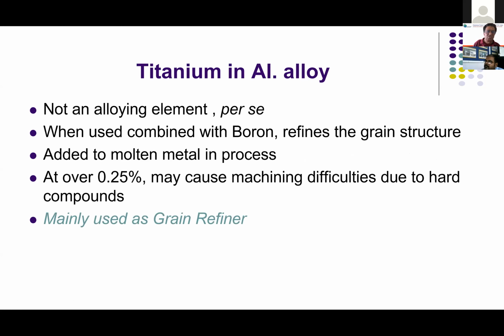Titanium, per se, is not an alloying element, but it improves along with the combination of boron at the ratio of 5:1, 5 parts of titanium and 1 part of boron. It improves the grain structure. Smaller the grain, higher is the strength. So therefore it improves the grain structure vastly. So we recommend titanium in most of the alloys between 0.1 to 0.15. In some cases, you go up to 0.2% titanium.